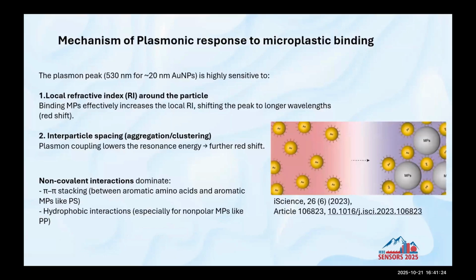The whole technique's mechanism is based on the fact that gold nanoparticles, when they are individual, have their own specific absorption wavelength. But when they are bonded to peptide and aggregate on the surface of the microplastic, first of all, their refractive index media will be changed. Second of all, because of the coupling between the frequency of the resonance, or the plasmon resonance as we call it, both together cause the wavelength of the absorption to shift to a higher wavelength. That's the way we developed this technique for the detection of microplastic.